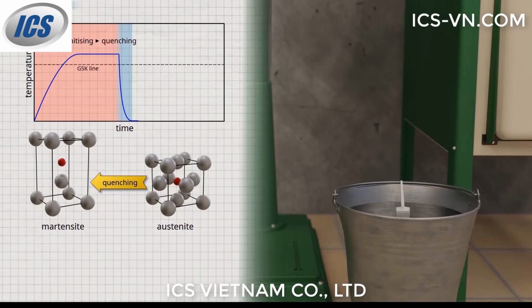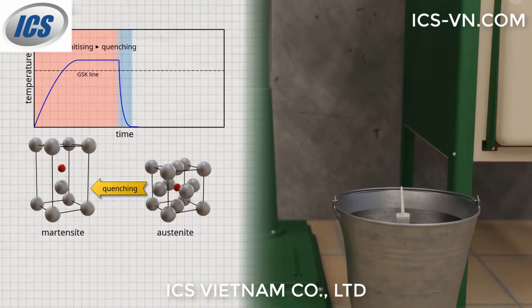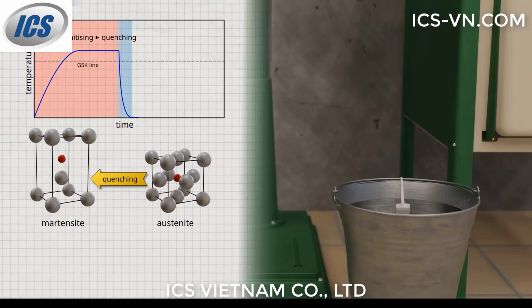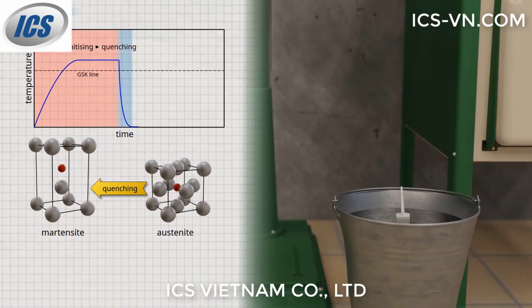This distorted microstructure is very hard, in contrast to the original ferritic microstructure. In addition, the lattice distortion leads to an extremely strong inhibition of dislocation movement. As a result, the formability of the steel is greatly reduced, while the strength is increased.